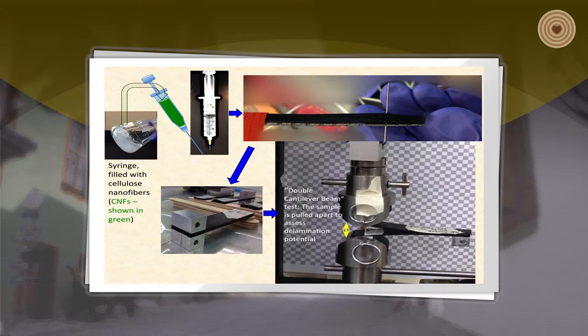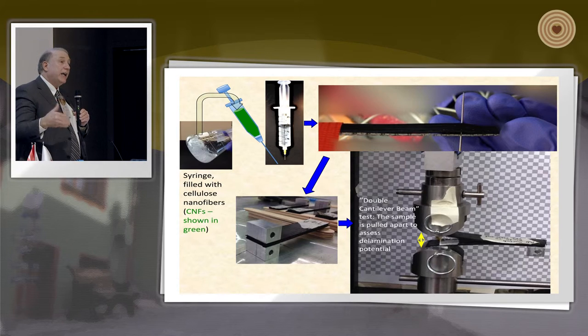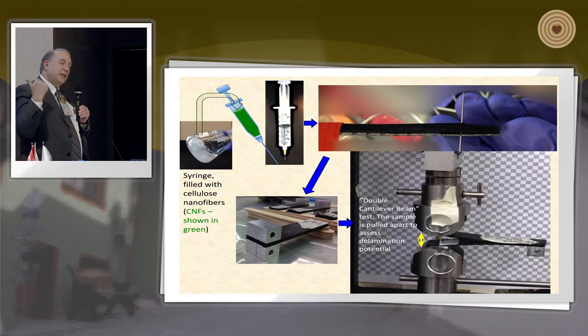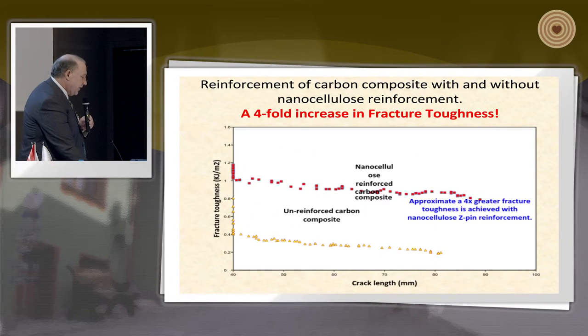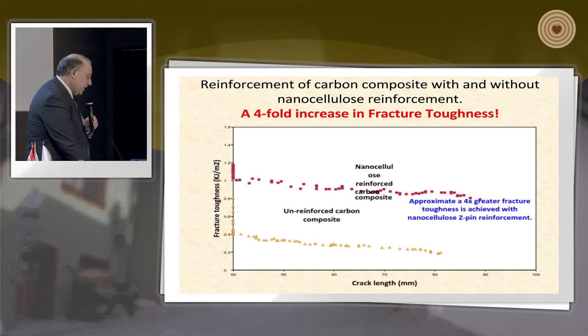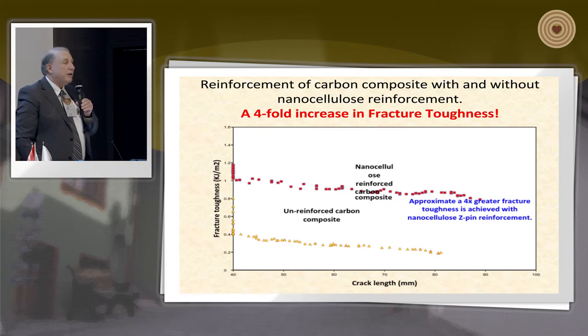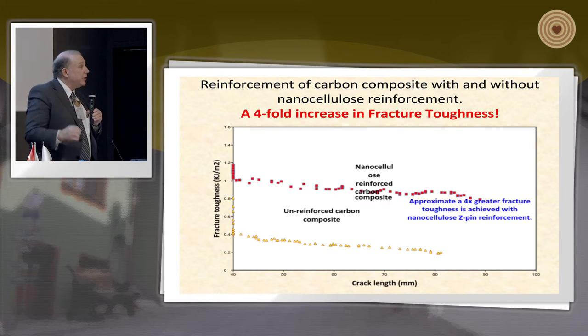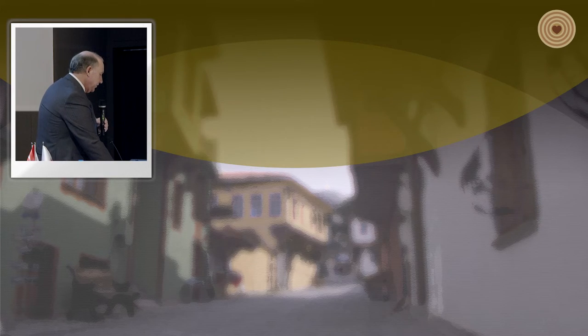We press the carbon fabric together in a hot press, heat it up, press to form the composite, and then pull the material apart to test its strength. One of the problems in military and high-end aircraft made from carbon composites is delamination. By adding nanocellulose to these composites, our preliminary data shows about a four times increase in fracture toughness for the nanocellulose-reinforced carbon composite versus the unreinforced composite — improving a space-age material by using a component of wood.